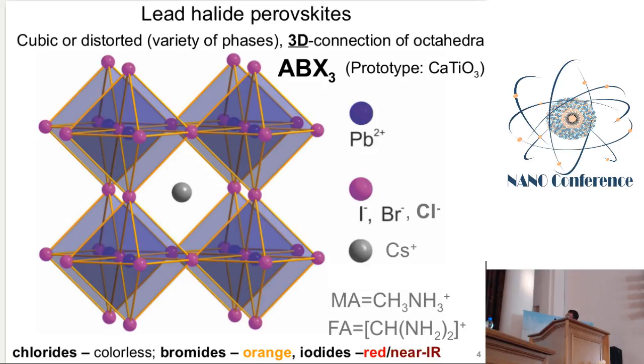Another very important part of this material is the metal ion. Normally we work with lead, and we also work with some less toxic materials as well. But this ion plays a very important role because the molecular orbitals of this central metal ion provide outstanding electronic coupling, and that's why charge transport. Then the cation part, which is a bit less important, can be either a monovalent organic cation or also a metal ion. Mostly this cation part is responsible for the chemical or morphological stability of such material.